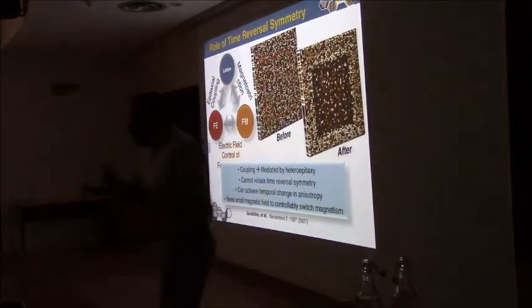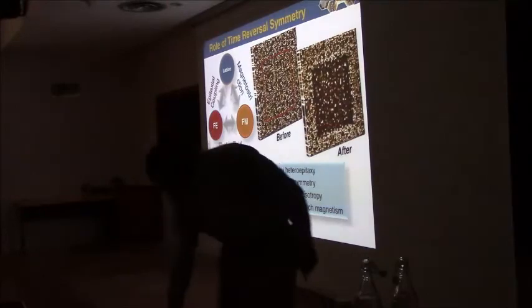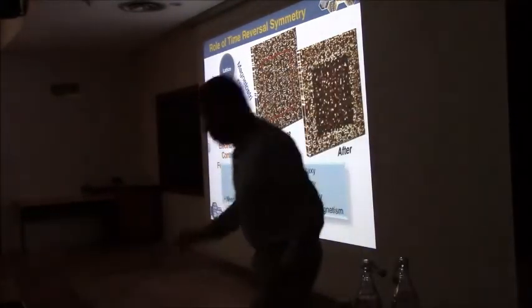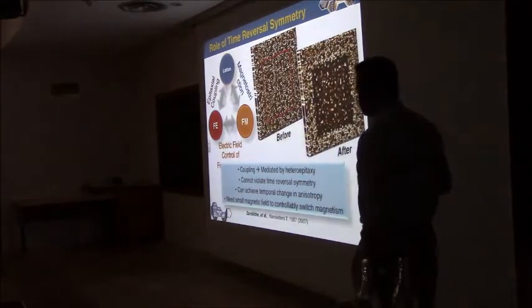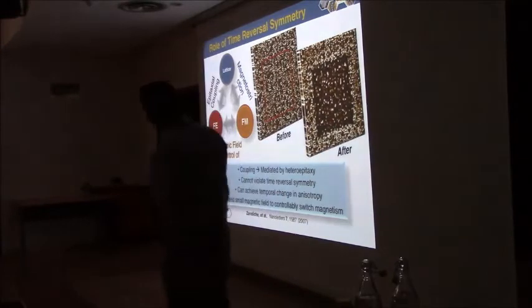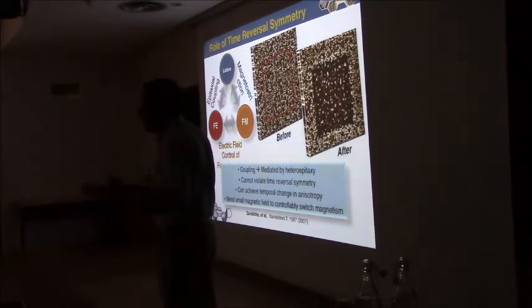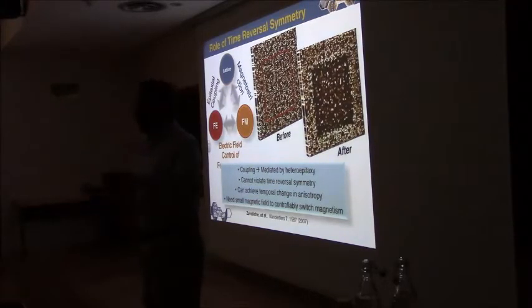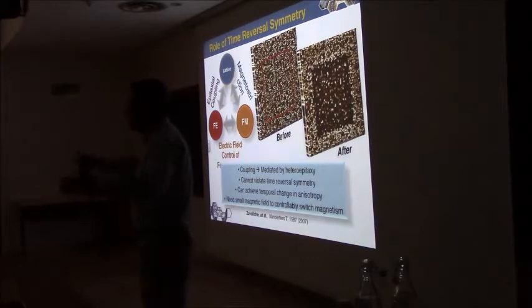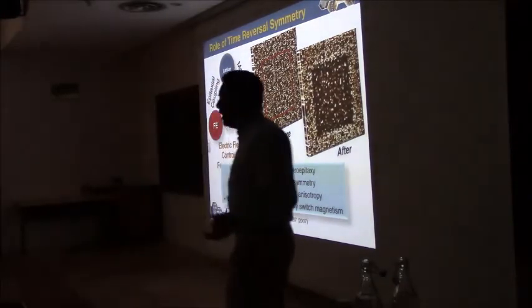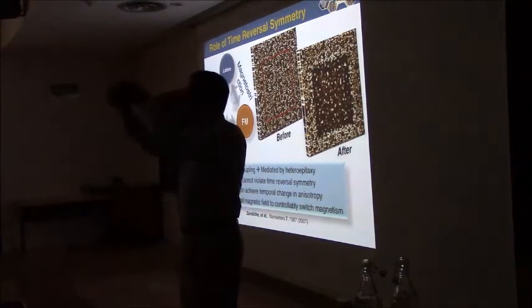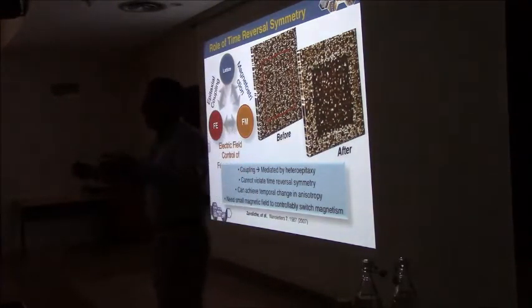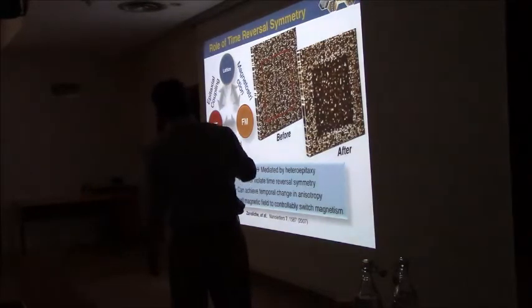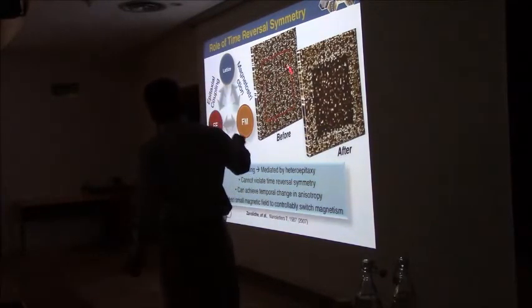Okay, we're now getting more and more into the physics. I want to use this slide to explain something which is really important, and this is mainly for the students, so the professors know all of this. About 12 years ago, we created nanostructures, and I didn't give you the full background. Think of a cigarette box, and a lot of people here smoke. Think of a cigarette box where you have two phases. One phase is a cigarette, the other phase is the air. You have an ordered array of cigarettes sitting in a rectangular box. So we created a nanostructure where you can have 20 nanometer type pillars of a ferromagnet or a ferrimagnet epitaxially embedded in a matrix, which is a ferroelectric. That matrix is all of these brown regions, and the dots you see here are the 20, 30 nanometer type pillars. These are magnetic force microscopy images.